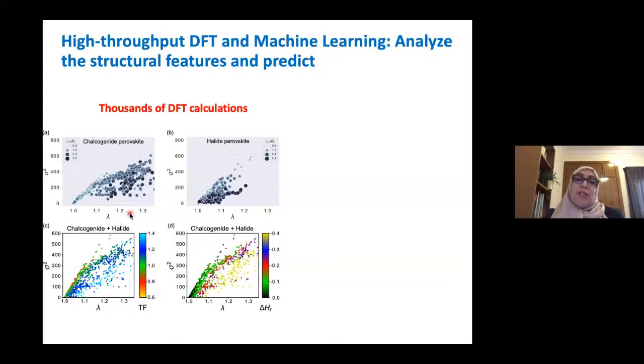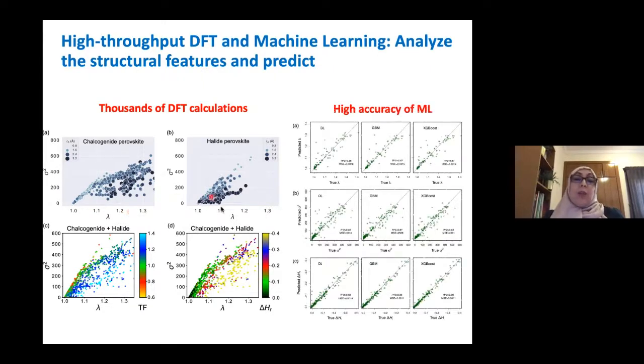In fact, what I want to emphasize is that these perovskites often degrade very quickly because they are intrinsically not stable. They're in a metastable state, and this is why, when we mix these cations and ions, we bring them closer to their stable position. And then in that case, we called again for the help of machine learning to try to derive some trends, to see what are the most important features governing this type of deformation, especially the impact of the cation. So we know that the cation is the best way to tune the stability of those materials without altering their optical properties in a significant way.